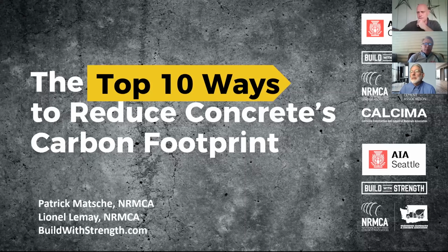That you don't want. But there are other reasons why that structure will probably deteriorate before the reinforcing begins to rust, right? So if you have a parking deck or a bridge deck or something along those lines that has poor quality concrete, it's likely going to deteriorate way before carbonation has an effect on it. I think my experience has been that as low carbon concrete with all the admixtures is coming about, your slab thickness is also being reduced somewhat because of the higher strength. So that's interesting. Sure.